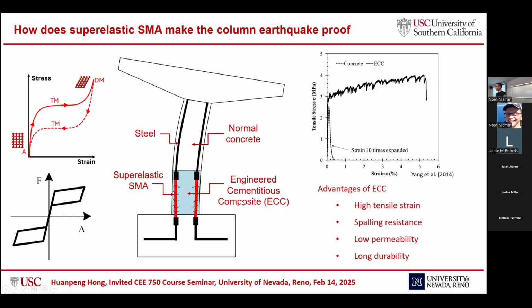This blue part is the engineering cementitious composite. It's the ECC. Because we know the shape memory alloy can deform up to maybe 10%, but the concrete cannot. If we load this column to maybe 20% of the drift ratio, the concrete spalling or the tensile cracking will just reduce the capacity of this column. So we need some kind of high performance cementitious material here. The reason why we use ECC here is that the ECC has really high tensile strain. Its tensile strain is maybe 20 or 30 or even 100 times higher than the conventional concrete. And also it has spalling resistance and low permeability and long durability.